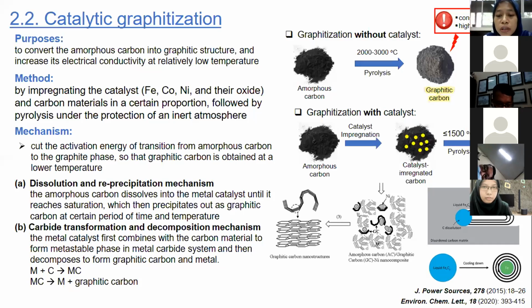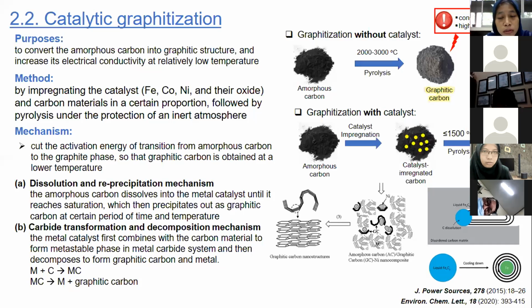Generally speaking, to convert the hard carbon structure formed in the pyrolysis process of biomass into an ideal graphitic structure without a catalyst needs a super high pyrolysis temperature, up to about 2000 to 3000 degrees Celsius. Super high temperature conditions consume a lot of energy and cost. But catalytic graphitization is proven to graphitize carbon and increase its electrical conductivity at lower temperature by introducing a catalyst into amorphous carbon. The graphitization catalyst cuts the activation energy of the transition from the amorphous to the graphite phase, so that graphitic carbon is obtained at lower temperature. Generally, catalytic graphitization is conducted by impregnating a catalyst like iron, cobalt, nickel, and their oxides with carbon material in a certain proportion, followed by pyrolysis under the protection of an inert atmosphere.